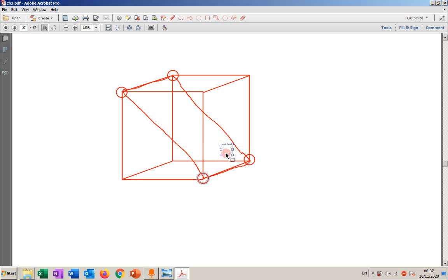We have them, and we said also we have one at this face, one at this face as well here. We said this was A here, and this side is root 2 A. So this is the FCC crystal structure, and the plane that we have is still 0, 1, 1, and we know that A is equal to 2 root 2 R.